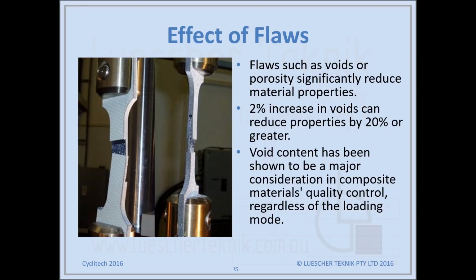So the effect of flaws. Flaws in the laminate, such as voids or porosity, have a significant effect on the properties of that material. So if you have greater than 2% of voids, your flexural strength can be reduced by 20% or even greater. There's lots of documentation on this over a long period of time on the effect of flaws. Lots of testing has been done. But basically, these flaws reduce the mechanical properties.